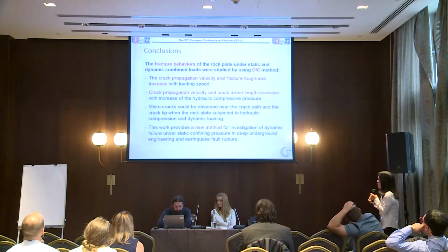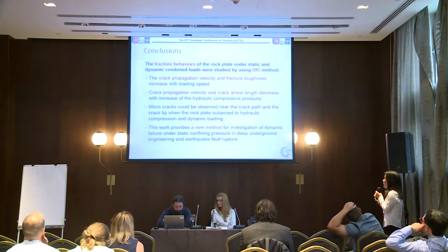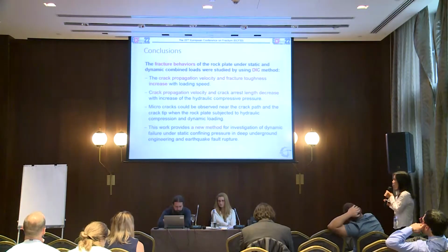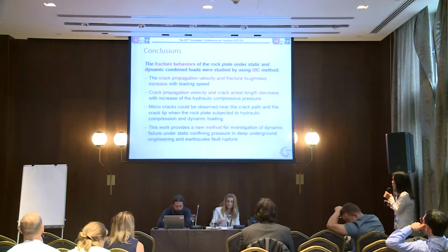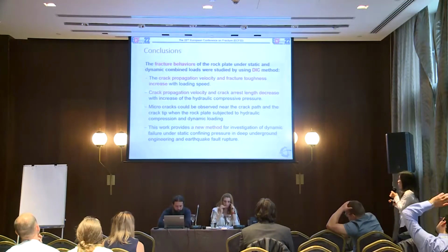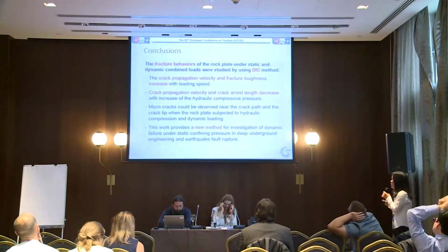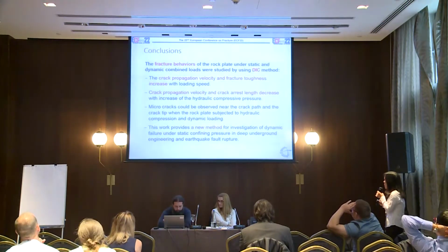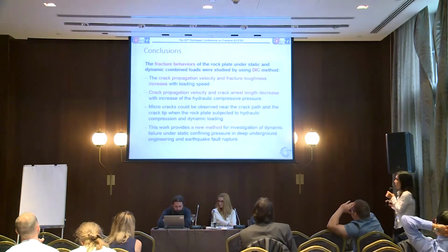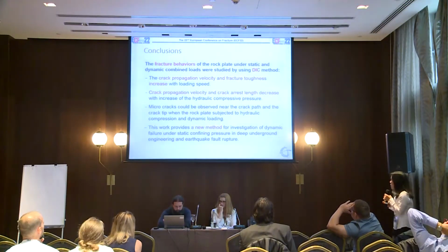Micro cracks could be observed near the crack path and the crack tip when the rock plate is subjected to hydraulic compression and dynamic loading. This work provides a new method for the investigation of dynamic failure under static confining pressure in deep underground engineering and earthquake fault rupture.